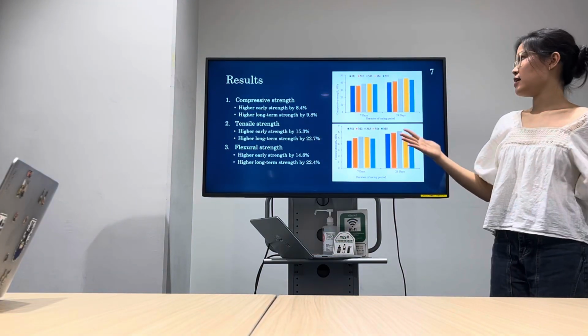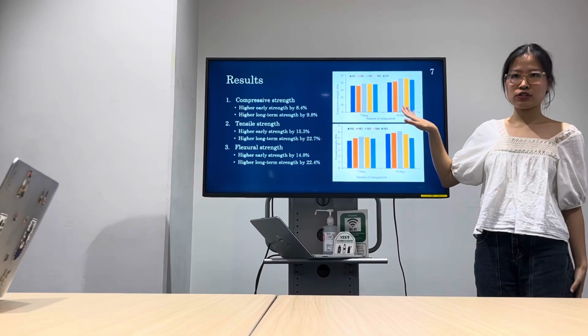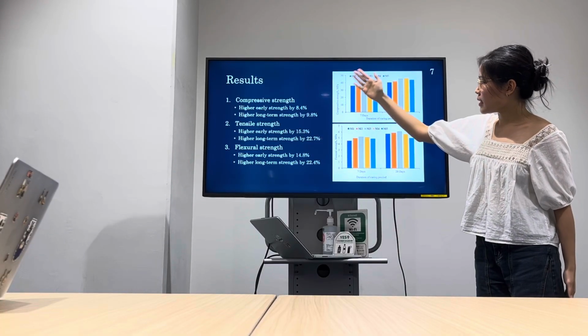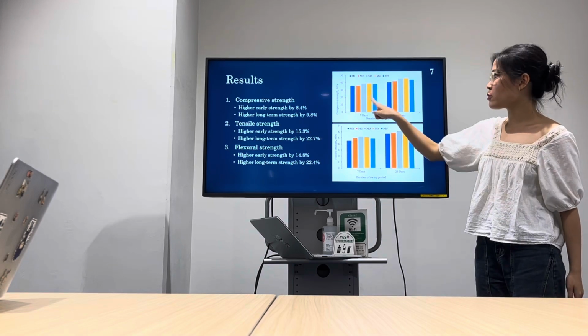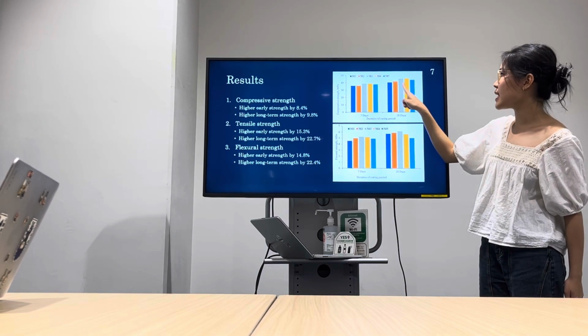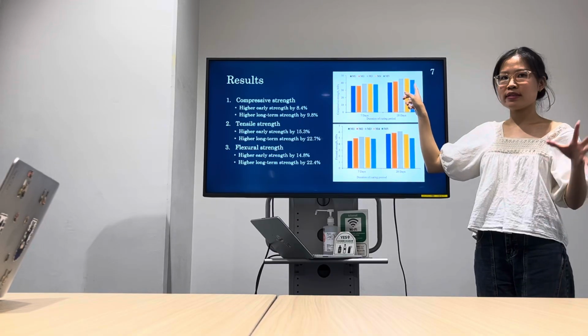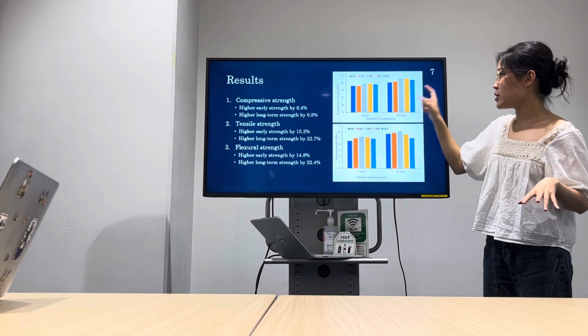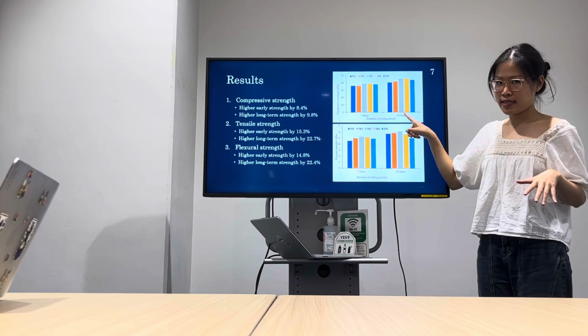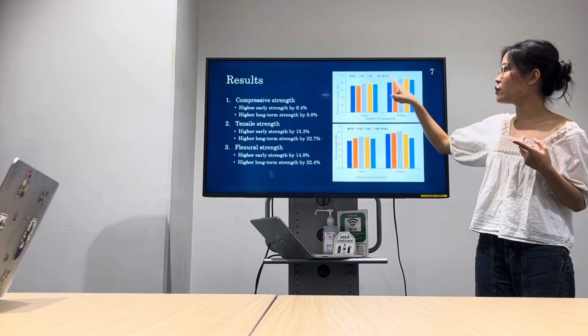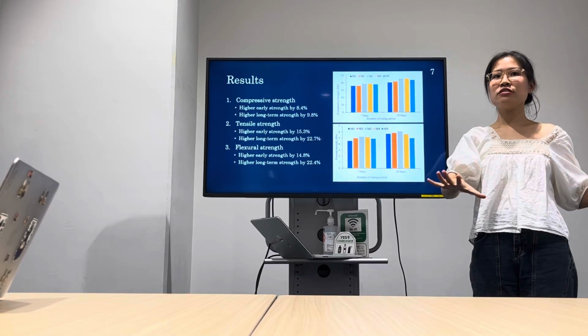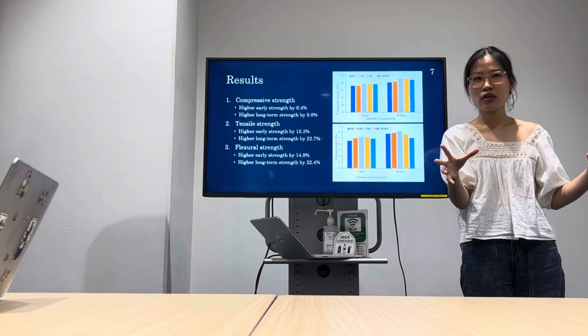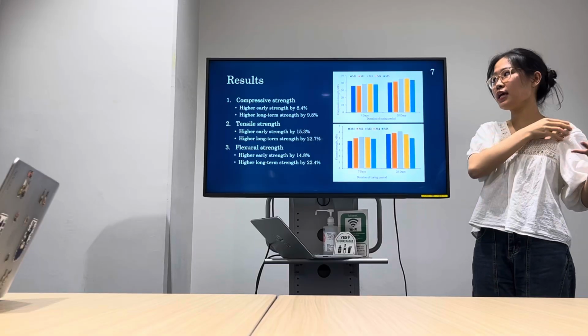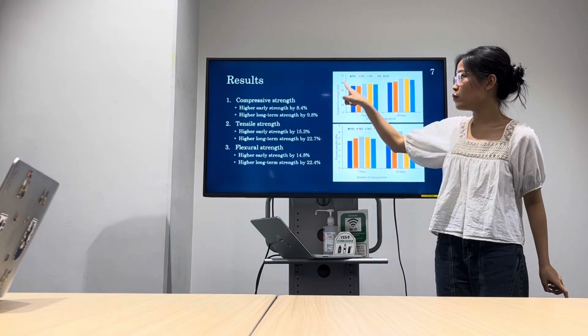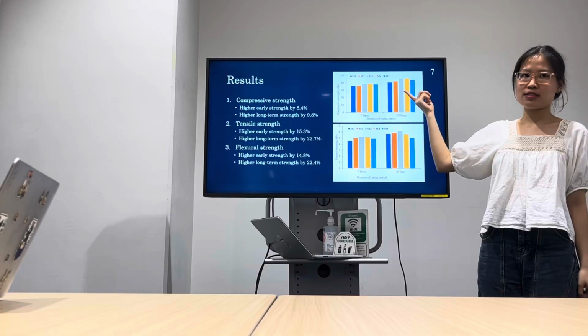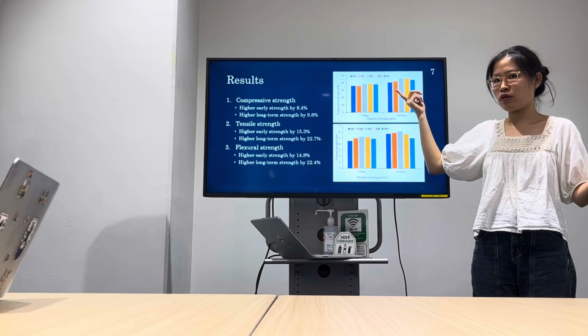For mechanical strengths, the first chart is the compressive strength. As you can see here, M3 and M4, both at 7 days and 28 days, demonstrate the highest compressive strength. Especially for 28 days, M3 and M4 are both over 40 megapascals. And mind you that the normal range of compressive strength for normal concrete is from 20 to 40 megapascals. So it already far exceeded the normal range.